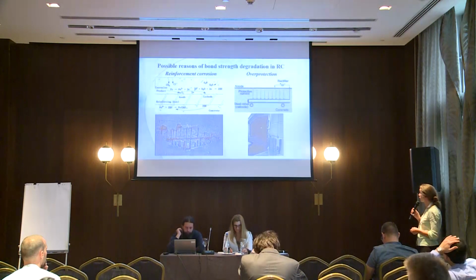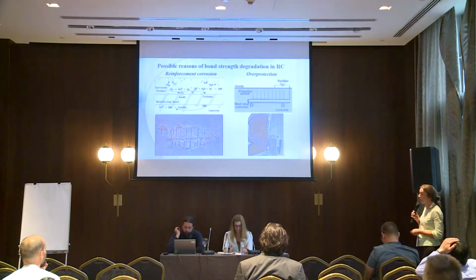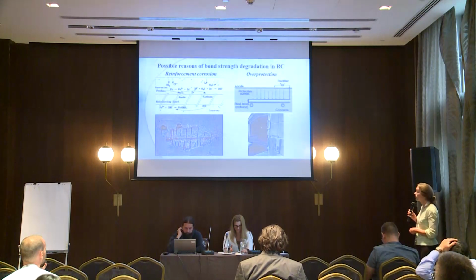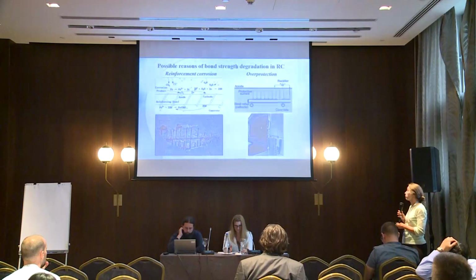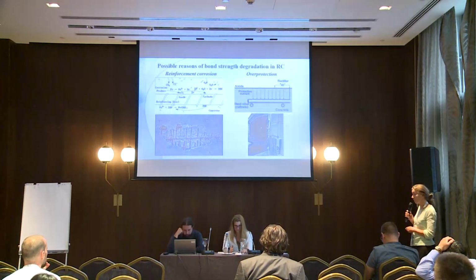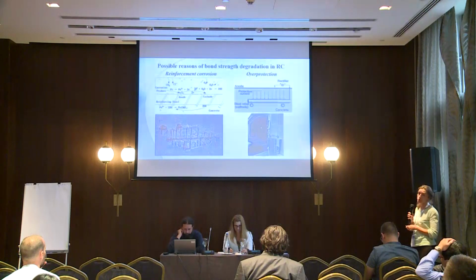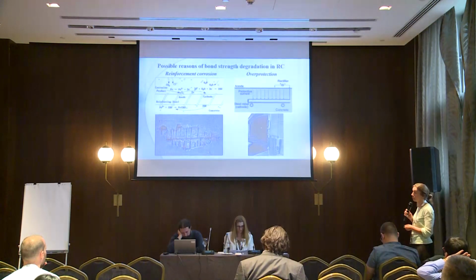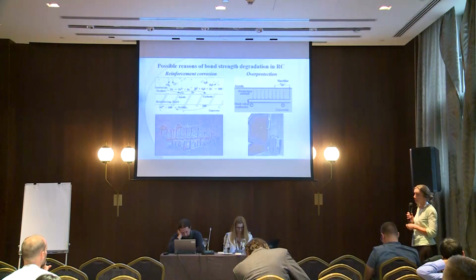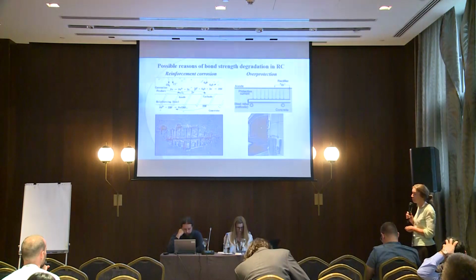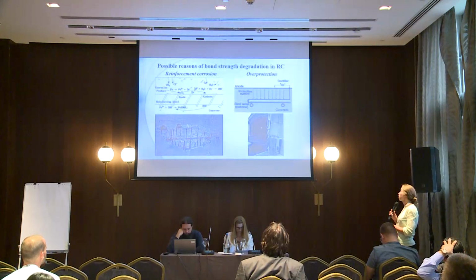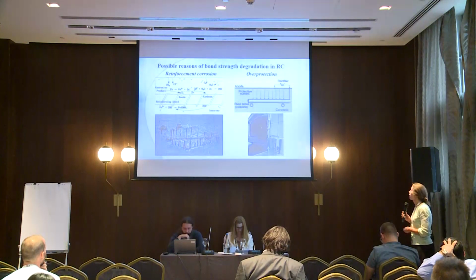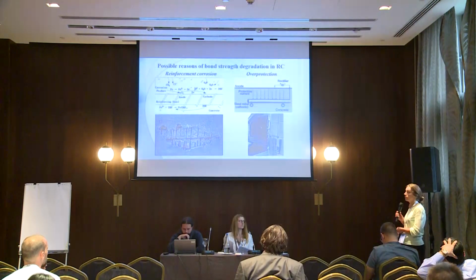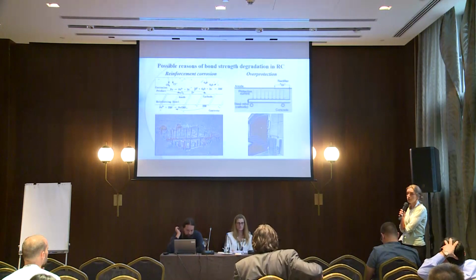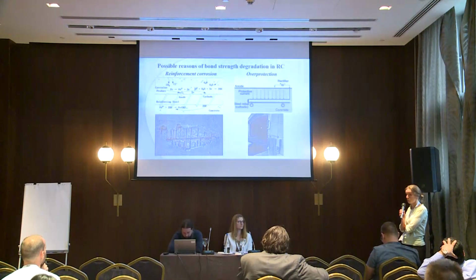Cathodic protection of reinforced concrete structures is a commonly accepted practice for reinforced concrete installations, for example, for bridges, and it is efficient for corrosion suppression in reinforced concrete, especially when an installation is operated in a chloride-contaminated environment. However, during cathodic polarization of steel reinforcement, hydrogen can be generated at the concrete surface. The role of hydrogen in structural integrity of reinforced concrete usually is reduced to consideration of hydrogen embrittlement of steel reinforcement.